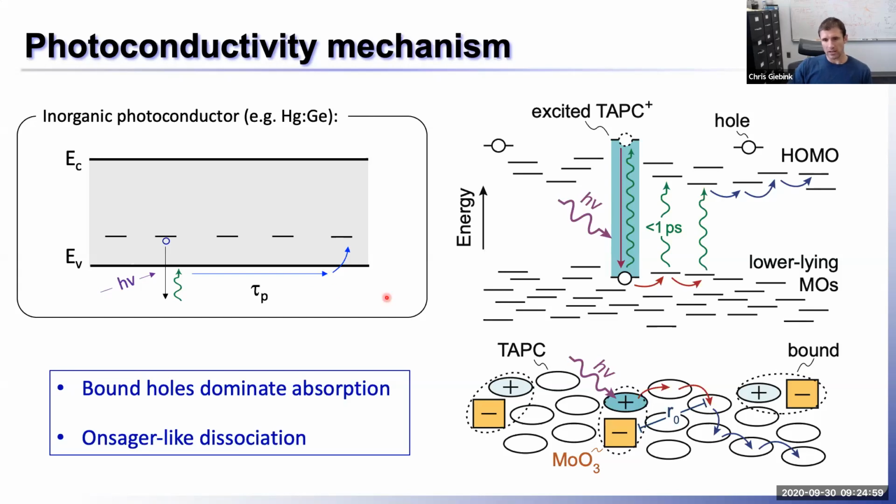In our case, the acceptor levels are actually the moly oxide counterion. Remember, we transferred an electron onto the moly oxide, and the residual hole is still strongly bound coulombically. The binding energy is hundreds of milli-electron volts. And so what we really created is a bunch of charge transfer complexes in their ground state.